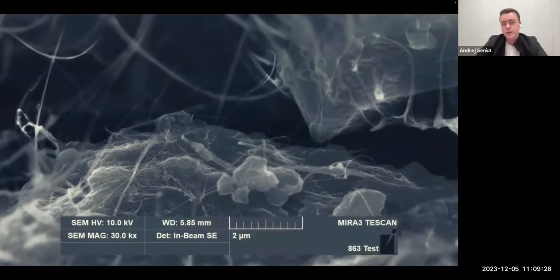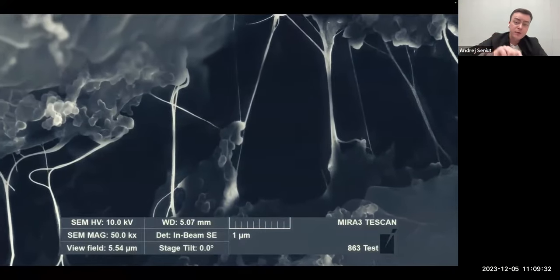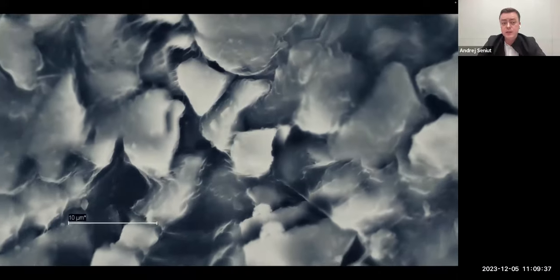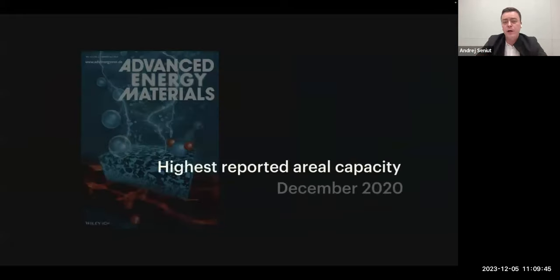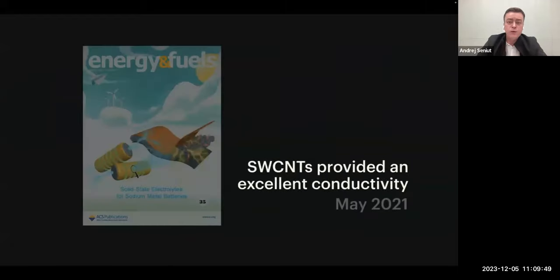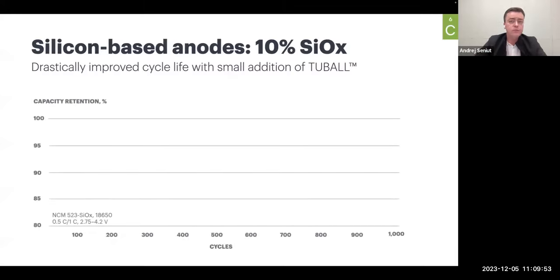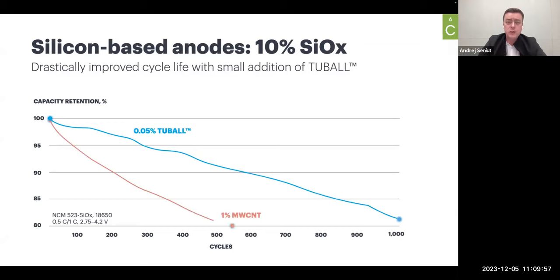And single carbon nanotubes, this is a real scanning electron microscope picture of silicon anodes, allow to create these bridges between silicon anode particles at a very long distance and assure that even when there is a very high volumetric expansion and contraction in your anode, the particles stay electrically connected, and thus the cycle life improves substantially. So this is one of the most typical results in silicon-containing anodes. In this case, I present to you a cylindrical 18650 battery with 10% of silicon oxide inside. But actually it's not that important which silicon material we are speaking about. Silicon carbon, even metallurgical silicon, it doesn't matter, because the principle is the same. Carbon nanotubes allow to create established connections between silicon anode particles in a very reliable manner. So the cycle life is improved substantially.